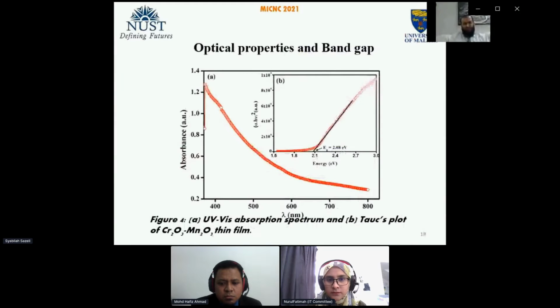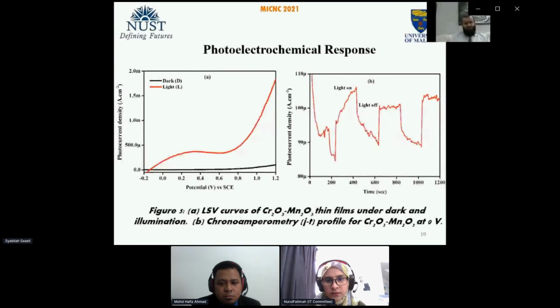The band gap of the thin films was confirmed from the optical band gap, where we plot the Tauc plot. The Tauc plot of the direct band gap shows the band gap is approximately 2.1 electron volt, 2.08 electron volt, which is very good for water oxidation. And therefore, the photoelectrochemical studies were performed. This is the linear scan voltammetry.